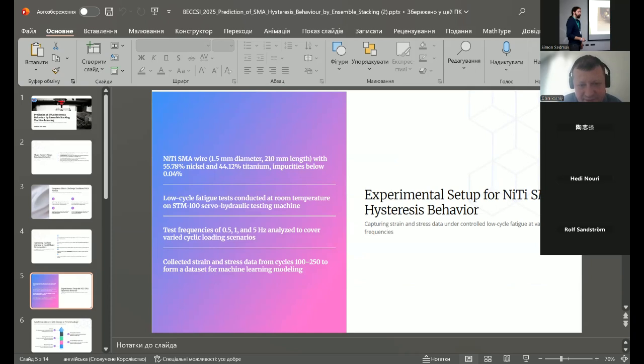In this study, we have employed experimental data of nickel titanium shape memory alloy wire with 1.5 millimeter diameter, 210 millimeter length, with roughly 56 percent of nickel and 44 percent of titanium with impurities below 0.04. Low cycle fatigue tests were conducted at room temperature on an STM 100 servo hydraulic testing machine. Test frequencies were equal to 0.5, 1, and 5 hertz, to cover varied cyclic loading scenarios. Collected strain and stress data from cycles 100 up to 250 were used to form a data set for machine learning modeling.